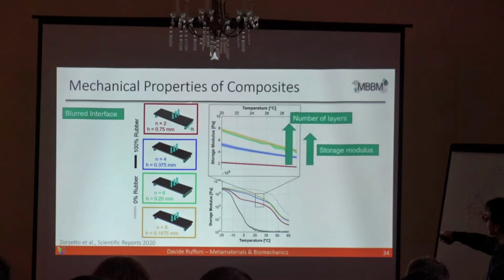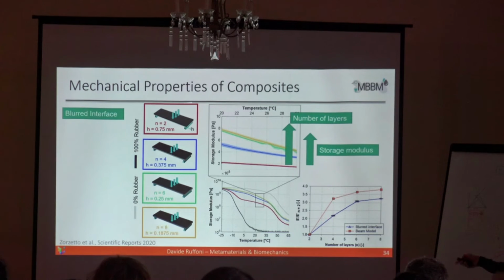So by increasing the number of layers, of course, you are redistributing the stiff material away from the neutral axis, and so you see an increase in stiffness, which was nice. The increase in storage modulus is the stiffness, let's say, which was nice, as expected, also in line with beam theory, if you want. Very simple.